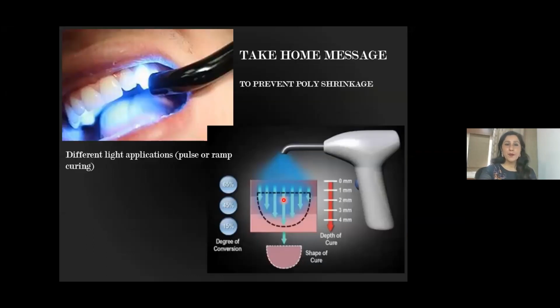So when you put your light cure probe, then what happens? The first layer gets the maximum light intensity. And as you go down, suppose it's a deep restoration, can you believe that the degree of conversion is only 15%? Your light intensity just decreases. So remember to check your light curing unit's light intensity at all times.